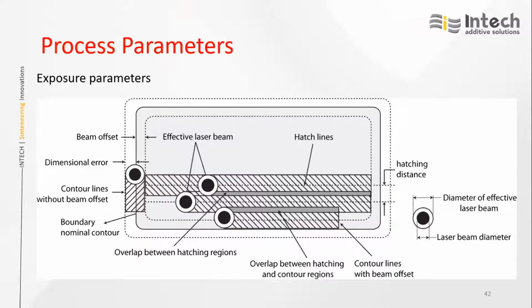If the hatch distance is not maintained properly, there won't be proper overlapping between two consecutive passes. If that is not happening, lack of fusion will occur. Two things to keep in mind: between two consecutive passes there should be proper overlapping within the layer, and between two consecutive layers, the present layer should get properly welded to the previous layer.